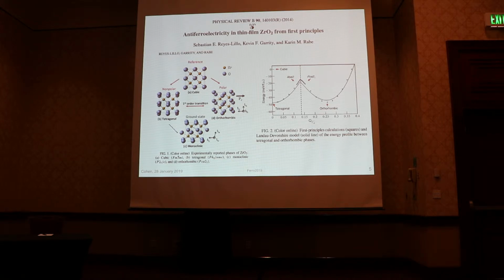So I'll just keep putting them up from different people's papers. But the key thing, I guess, is that the high temperature, high symmetry phase is fluorite. So instead of thinking about starting from perovskite, like many of us are used to thinking of, we start from the fluorite structure, which is also a very symmetric, nice, simple structure. And it just has many distortions.